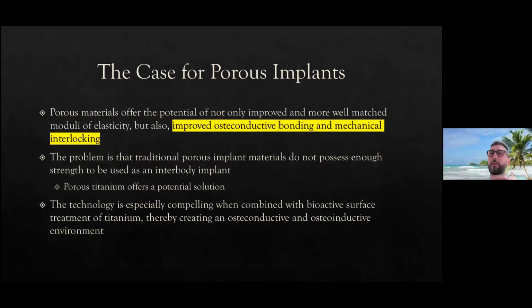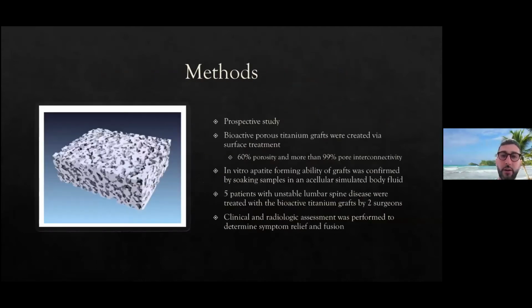But basically, they talk about this concept that porous grafts in general are very favorable because of osteoconductive bonding, right? It serves as a scaffolding for bone to grow. But the problem is that what we were using traditionally for implants like PEEK, they're just not strong enough. If you make them porous, they're just going to break, right? So porous titanium offered a solution. And what these authors say is that if you combine that with a bioactive surface, in other words, a surface that has not just osteoconductive properties, but osteoinductive properties, that you're really optimizing your graft.